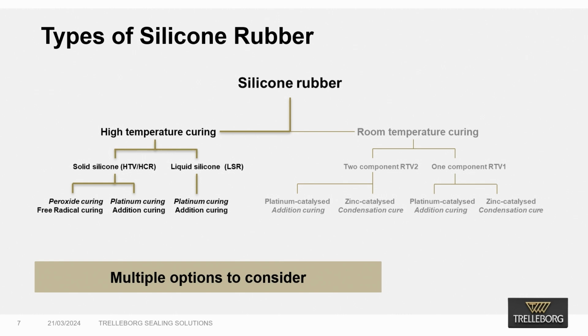But the real key point of what I am talking to you about today is the high temperature curing materials. Now, these are split into two. We have the high consistency silicone rubber, which is either referenced as HCR or HTV, and we have the liquid silicone rubber, both of which are critical to everything that Trelleborg are doing for our customers. Now, we break those down further. High consistency silicone rubber can be catalyzed via ionic chemistry with peroxides or addition chemistry with platinums. LSR can only be catalyzed with platinum, and this gives rise to some differences to consider, but there are multiple options. So what are the differences between HCR and LSR?